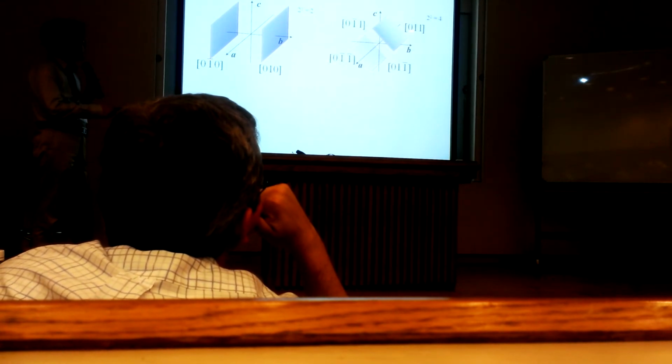And shown here are the multiplicity factors. The reason for the multiplicity factor comes from the identical d spacing between planes. For example, if you have a 0, 1, 0 plane, you also have another equal-spacing plane, 0, minus 1, 0. So the distances are identical, but you just count once in your structure factor, so you need to multiply by the number of these identical planes. Here is another example for the 0, 1, 1 and the 1, 1, 1 planes.